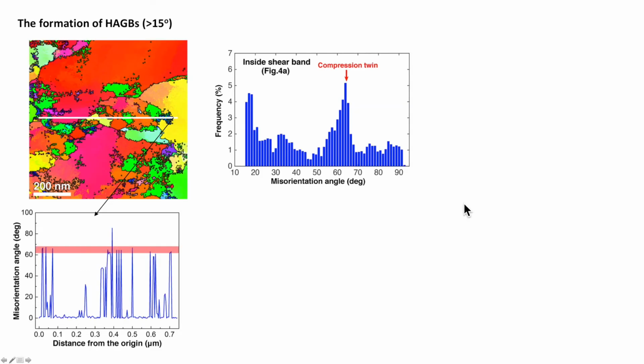For those who are familiar with titanium, we know alpha titanium has HCP structure. This tells us not only dislocations can contribute to the plastic deformation, deformation twins can also be prevalent in the deformed microstructure. We also know for HCP crystals, there's extension twin and compression twin. We'll look at those one by one. Let's look at the shear band first. When examining the grain boundary misorientation histogram, you can see there is a peak around 60 to 64 degrees, and this misorientation corresponds to the compression twins in HCP crystal structures. This tells us the compression twins are also present in the shear band.